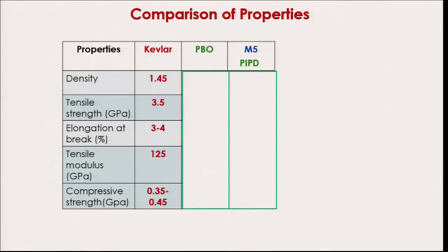So, if I look at the properties of this fiber, that is Kevlar fiber, it has a density of about 1.45, strength 3.5 GPa, very high, elongation at break is 3 to 4% like in the case of polyethylene, the tensile modulus is 125 GPa, very high. Compressive strength is not good, compressive strength is low, 0.35 to 0.45 GPa. That means, for applications where you need to bend them, it leads to some kind of kink formation and the compressive properties are poor.